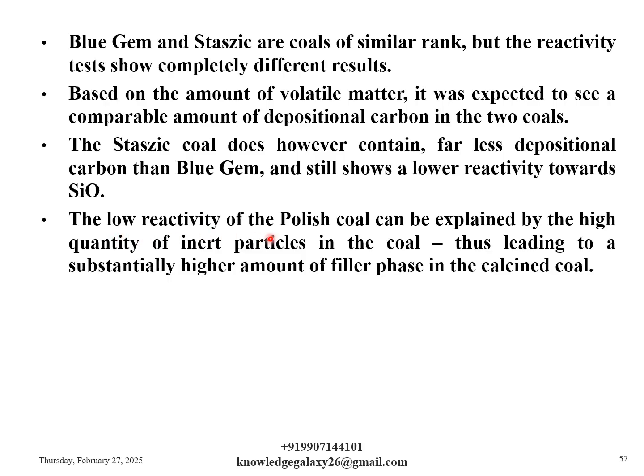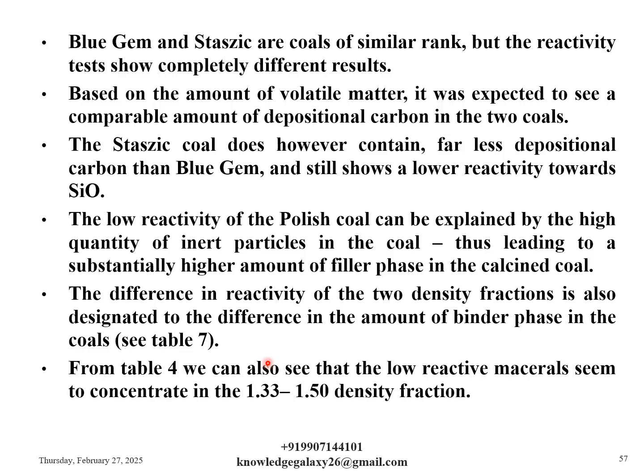The low reactivity of the Staszic coal can be explained by the high quantity of inert particles in the coal, thus leading to a substantially higher amount of filler phase in the calcined coal. The difference in reactivity of the two density fractions is also attributed to the difference in the amount of binder phase in the coals, as can be seen from table 7. From table 4, we can also see that the low reactive macerals seem to concentrate in the 1.33 to 1.50 density fraction.